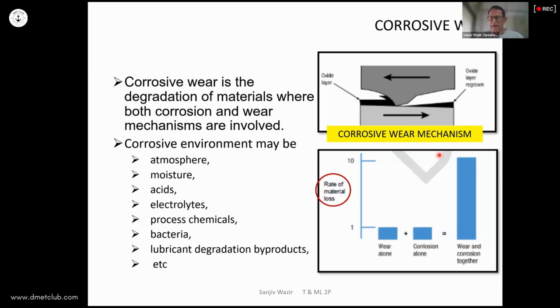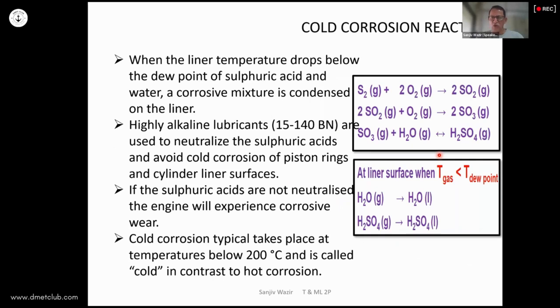One of the areas which was more prone, it's slowly going back into the background because the sulfur content of our fuels is less. But all along until about 2020, of course, we were always running engines with stoichiometrically excess oxygen conditions. So all the sulfur in the fuel would get oxidized. And these reaction rates are different for different temperatures and pressures. So about 15 to 20% of the sulfur would eventually end up forming sulfur trioxide. And water is also, of course, a product of the combustion of the hydrocarbon fuel. H finally forms water. So water is around, acid gas is around.